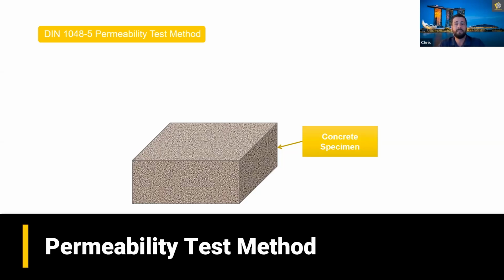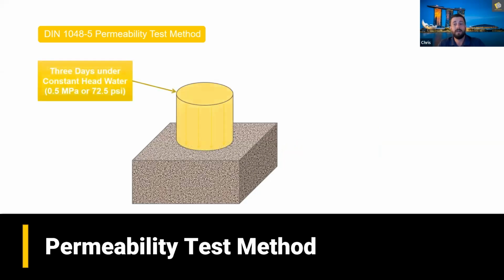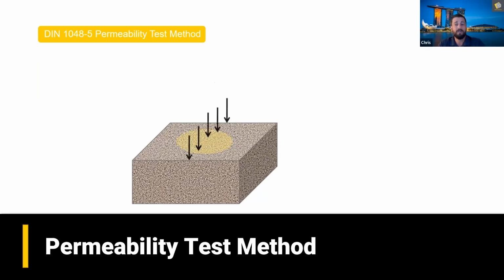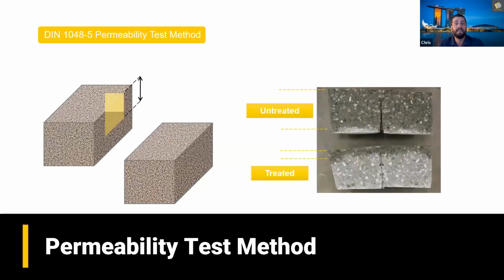Now, the test method is as follows. You cast and cure the samples, and the test is normally carried out when the age of the concrete is 28 to 35 days. You place the samples into sample holders. Apply water pressure of 72.5 psi on one end of the concrete specimen, while the other end is free to normal atmospheric conditions. Keep the pressure on for 3 days. Next, split the concrete samples and measure the average depth of water penetration.